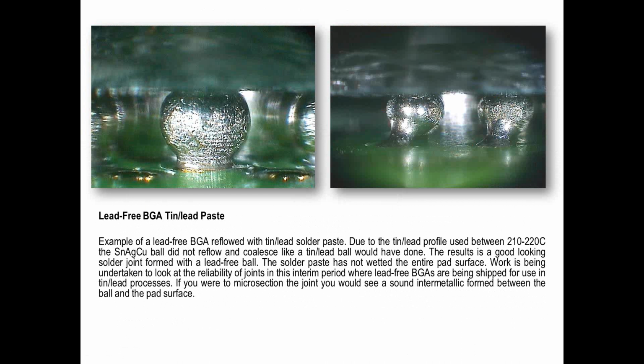I have to say, in all honesty, that the one on the left-hand side was a perfectly good joint. It never ever failed after quite a few years in service, but it didn't look right. And it's clearly what's happened is the tin lead solder has soldered to the high temperature ball and made a joint. But then again, what's different between that and a typical high temperature ball on a ceramic BGA? We have a high temperature ball, we soldered to it with tin lead, it will look exactly like that.